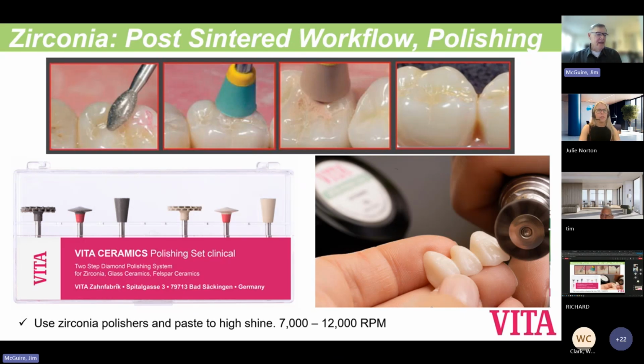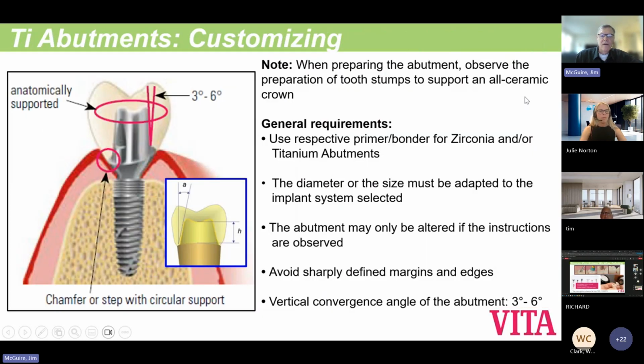So if you ever want to see what type of energy there is, you can take a zirconia crown, adjust it, turn off the lights, adjust it, and if sparks are flying, you know you're too high on the RPM, too much pressure, maybe a dull diamond burr. So make sure you adequately adjust for zirconia. Same with sandblasting. Part of the bonding protocol is you need to sandblast your restorations to have a little bit of micro texture for mechanical retention. If you've got your PSI, your bar high enough that in the dark, you sandblast it and it sparks, you know you're too high in pressure, and you need to reduce it and be careful on that.